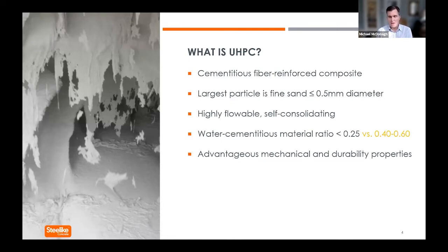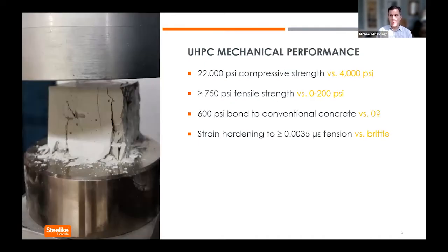A lot of the UHPCs, including Steel-Like, have an even lower ratio, around 0.18, 0.19, and it has advantageous mechanical and durability properties, such as a very high compressive strength at 28 days of around 22,000 psi versus, say, 4,000 psi for conventional concrete. It has significant tensile strength, and that will depend on how much steel fiber you put in it, but a typical benchmark is a minimum tensile strength of 750 psi. It bonds extremely well to conventional concrete. In most applications, the substrate concrete will fail before the interface will fail if you're doing pull-off testing. And thanks to the steel fiber, it also has strain hardening behavior, a property normally associated with metals, but it can undergo strain hardening up to a strain around 0.0035 in tension.